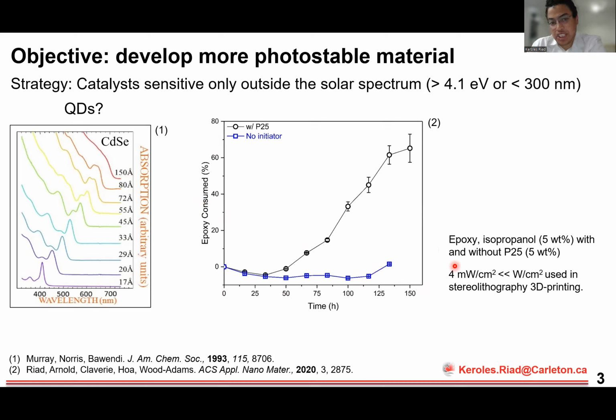And in blue, when you don't have initiators, you don't see any reaction. But when you add P25, which is a mixture of anatase and rutile titanium crystal structures, and it is a gold standard for catalytic activity, you see a typical photocuring pattern. Now, the problem here is that P25 and titania's bandgap energy is within the UV region. So that region is still unstable under sunlight. And so the next step is to make the quantum dots with the right bandgap energy, which is above 4.1 electron volt or lower than 300 nanometer wavelengths, which is what brings me to this work.